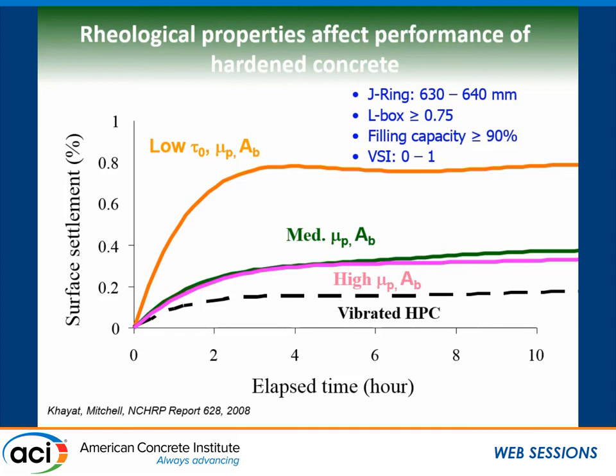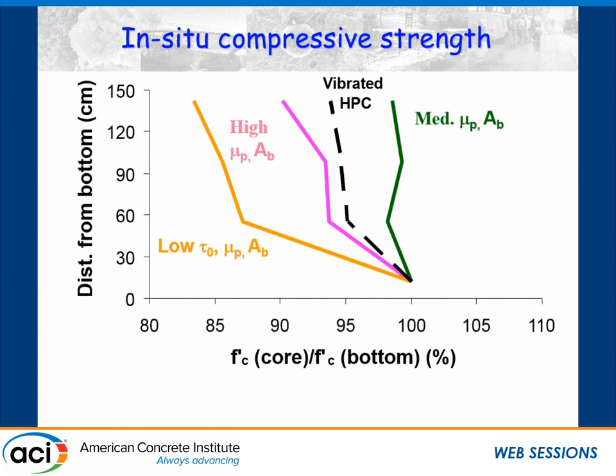So this is one concrete that has low yield stress, low viscosity, low thixotropy, surface settlement about 0.7, and this is a medium, and this is high, and this is the reference vibrated concrete. And if you look at the compressive strength of a core at a certain height versus the bottom, you see that this concrete here that has low surface settlement is very good, almost the same compressive strength in situ. The one that was very surprising is this one. Although the surface settlement was very low, it develops in situ properties that are inferior to the bottom. Okay? And then if the surface settlement is not adequate, then you obviously have heterogeneous distribution of mechanical properties.